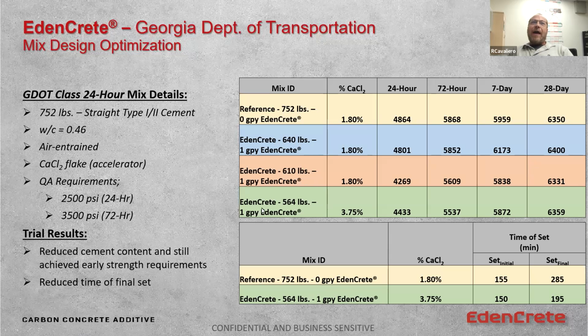So then we increased the chloride a little bit, and we brought it back to a good number here that we felt safe with. We dropped 192 pounds of cement per cubic yard out of this mix.